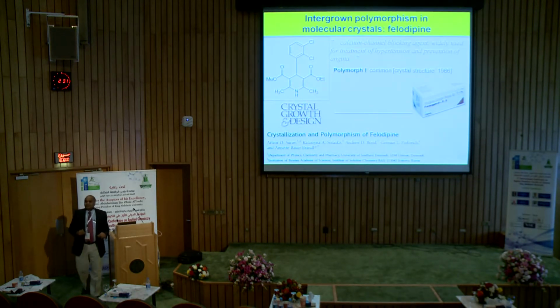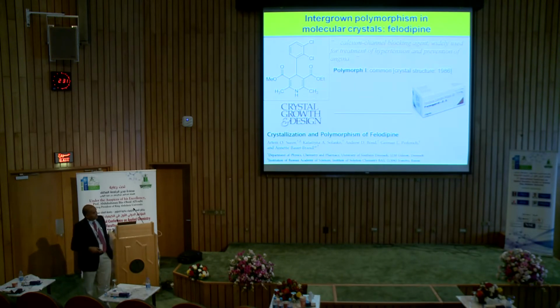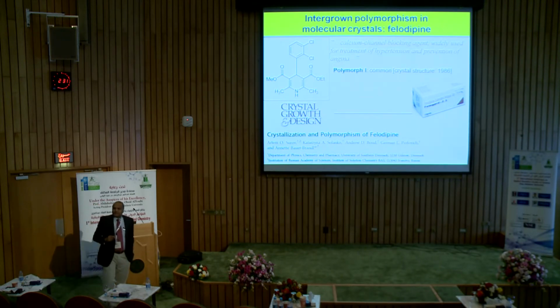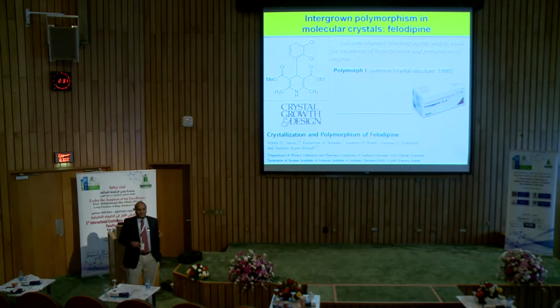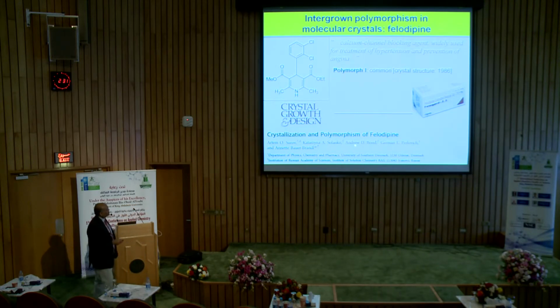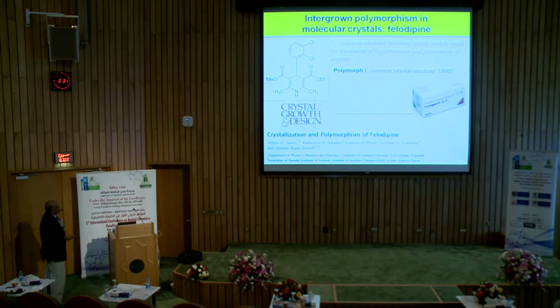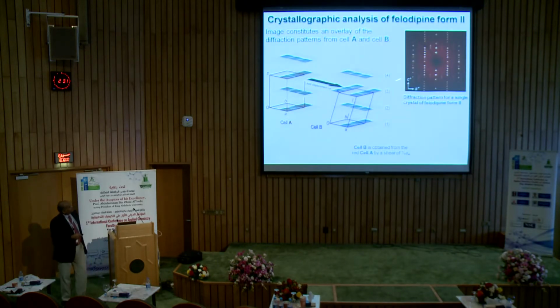So the aspirin was actually accidental work. We didn't really set out to do it. So then we looked at another important medicine, felodipine, which is again extensively used. Here again you get these kinds of polymorphs. This is work done with Andrew Bond, who used to be at Copenhagen, but he moved to Cambridge. So again, for those crystallographers, if you are interested, this is the kind of form you can have. You could have one material, form 1, where the crystal structure is like this, but you could also have a form 2 where the cell B is sheared, right? It's like this, and I sheared it, okay?